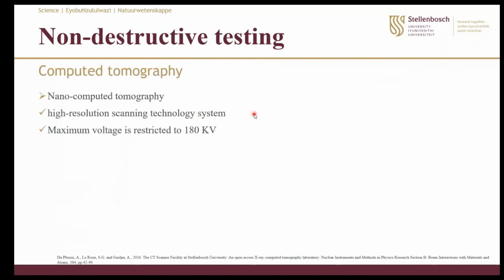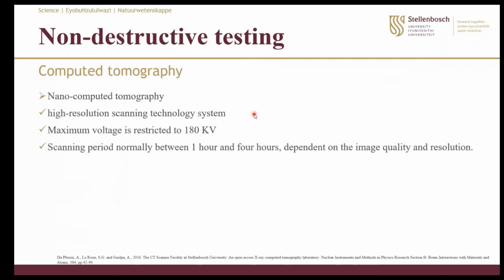And it has a maximum voltage that is restricted to 180 kilovolts. And because low energy X-rays can be stable over a long period of time, the scanning period for this type of method normally lasts between 1 hour and 4 hours, depending on the image quality and the type of resolution that we'll be looking at.